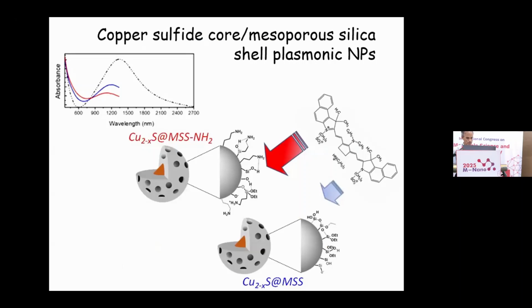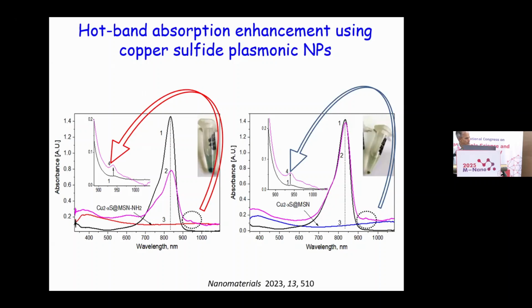So the schema of interaction of specific dyes and the surface of nanoparticles is shown here. Because mesoporous silica contains different groups like amino groups, sulfur, nitrogen, and so on, they can interact both by terminal groups and by mesogroups with the surface of these nanoparticles. And so we observed, when we realized the interaction of near-infrared dyes with copper sulfide nanoparticles, we indeed observed the enhancement of the hot band absorption, shown here.